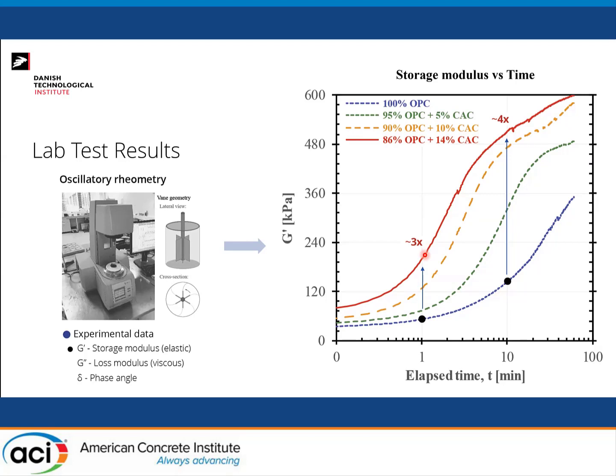But the advantage is, if I compare this data with a shotcrete accelerator, for example, I would have a much steeper slope of the evolution of G prime, even for the first minute, which could impose, or not could, it does impose some problems on handling and safety of a mixing nozzle.